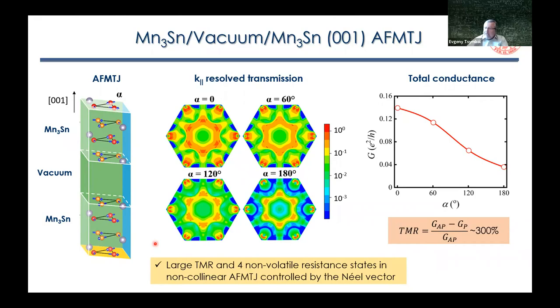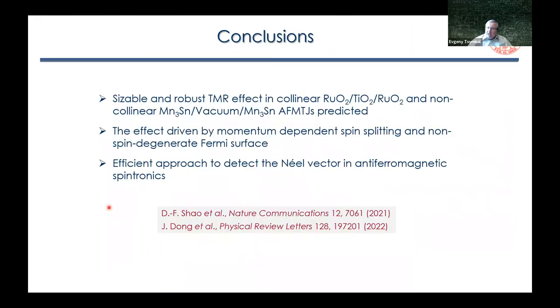All right, so I think I'm coming to the end of my presentation. What I would like to say in conclusion is a few things. First of all, we can see from this analysis that we can have a sizable and robust tunneling magnetoresistance effect in both collinear and non-collinear tunnel junctions if you are using antiferromagnets which have momentum-dependent spin splitting, and as a result, a non-spin-degenerate Fermi surface. The effect is quite similar to what we have in crystalline tunnel junctions, where we have K-parallel conservation.